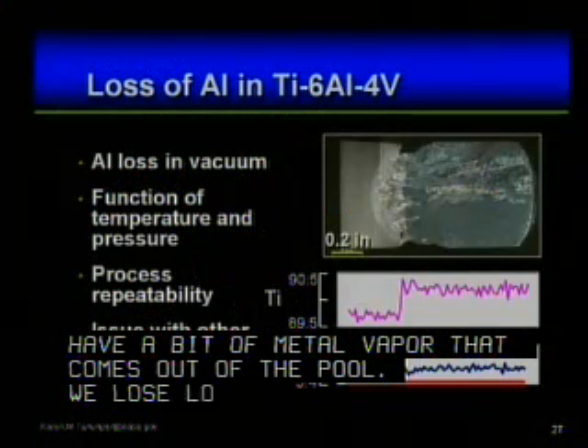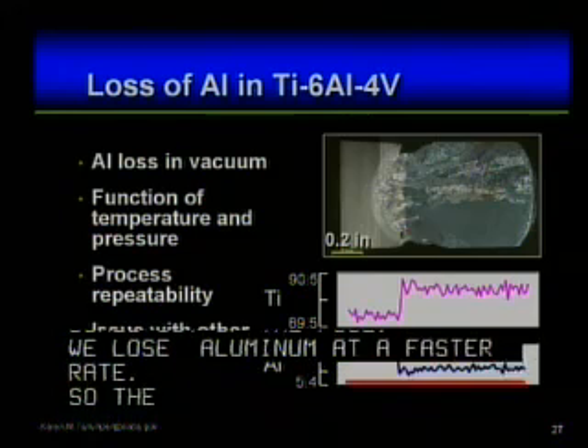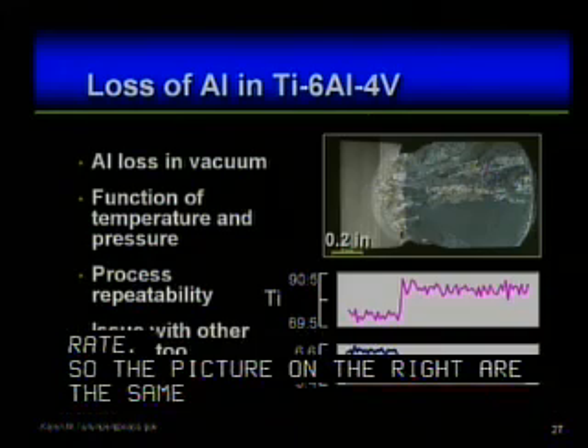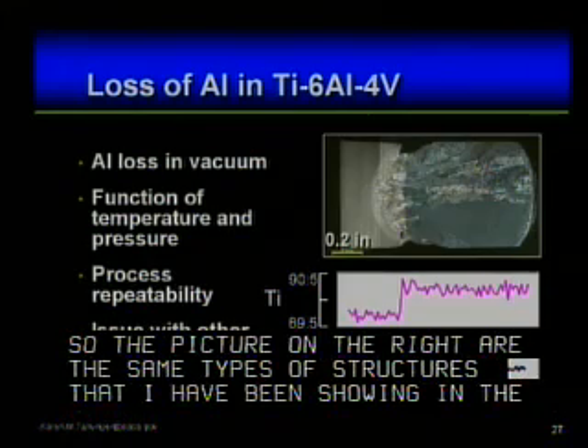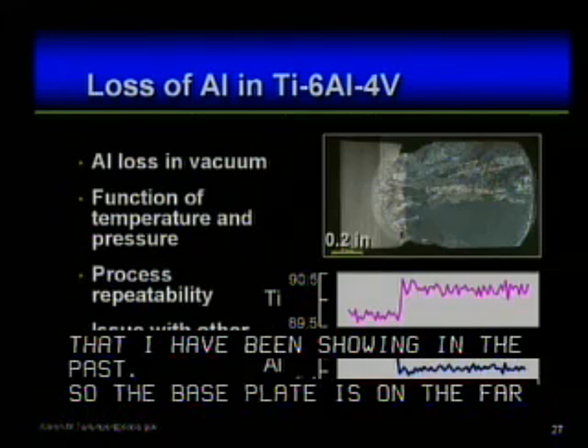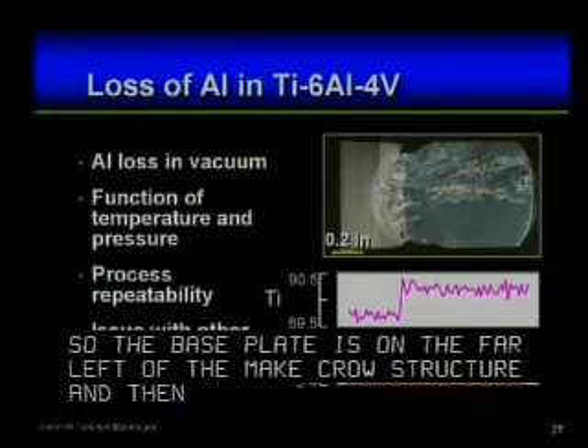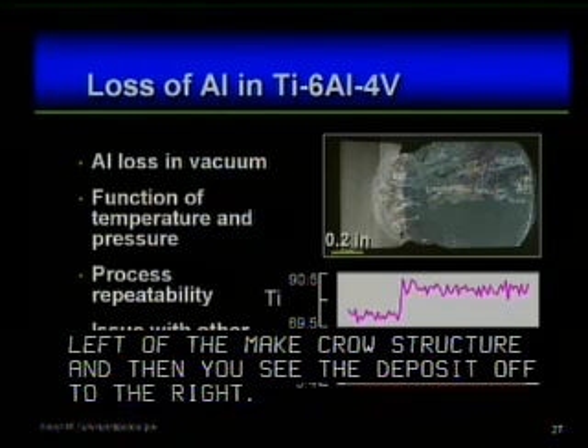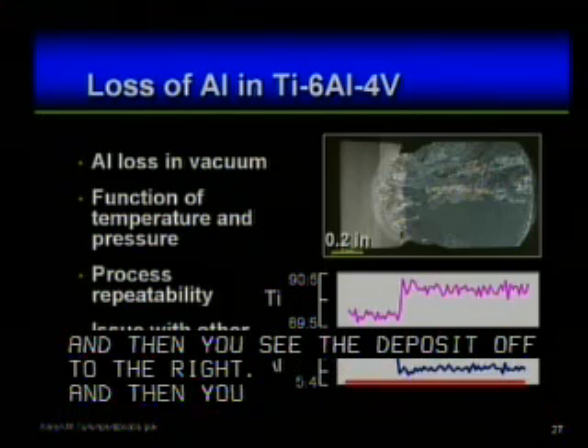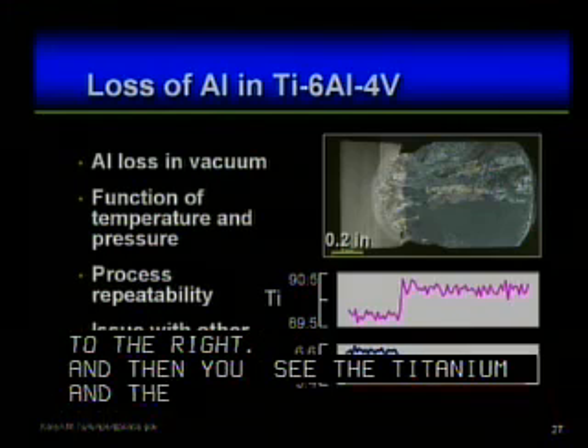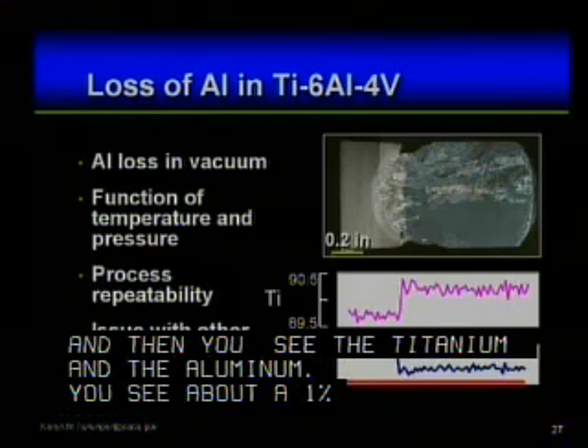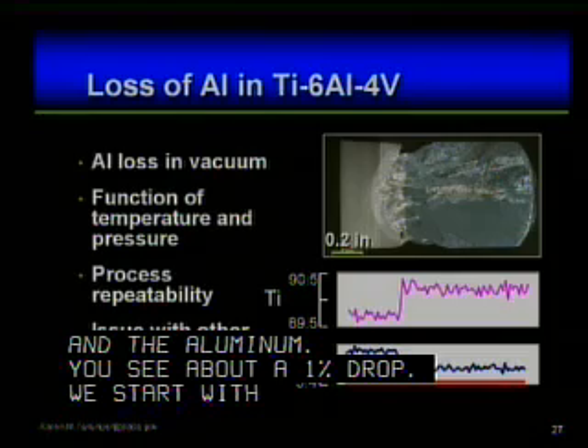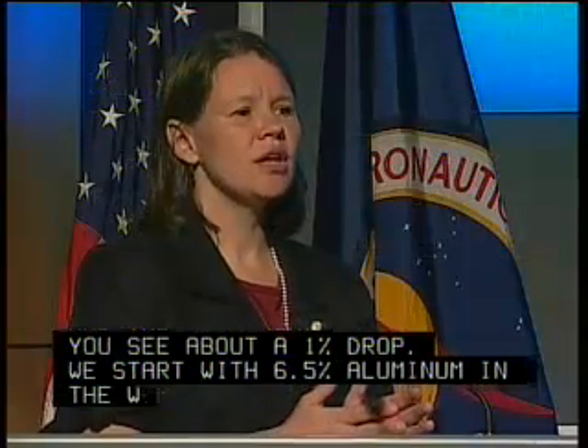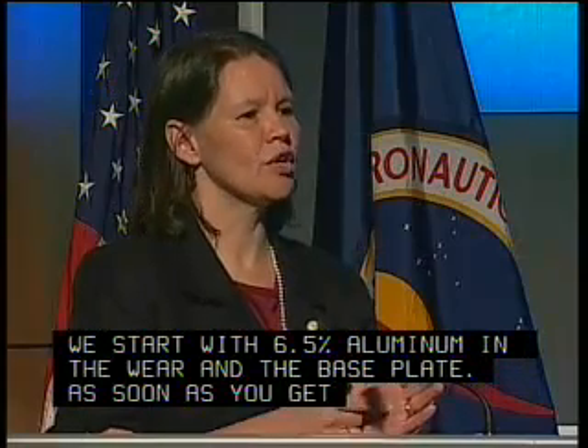So the picture on the right is the same types of microstructures that I've been showing in the past, only it's now laying on its side. The base plate is on the far left of that microstructure, and then you see the deposit off to the right. And the two lines below it, you see a titanium trace and an aluminum trace. This is just looking at the chemistry along the center line of that deposit. The vanadium didn't change, but the aluminum, you see about a 1% drop. So we start with 6.5% aluminum in the wire and the base plate. As soon as you get melting, whether it's in the wire or the base plate, you see that step function drop in the aluminum content because we've melted in a vacuum.